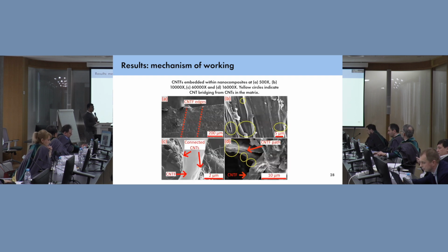And some more images just to show this with our carbon nanotube fibers. We took it for metallic electrodes, and then we take it for our carbon nanotube fibers. In this case, if you look really closely, I hope you're able to see that we have a little bit of directional alignment. This is where our carbon nanotube fiber is. We zoom in and look at it a bit closer in a different place, and we're able to see, okay, our carbon nanotubes from our matrix are actually adhering to the surface.